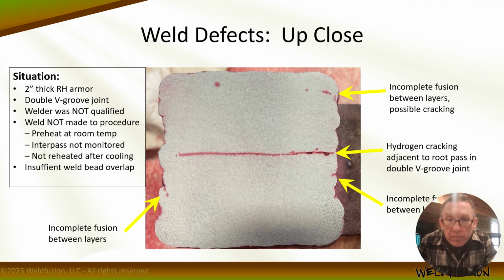Preheat was done at room temperature. Interpass temperature was not monitored between passes or after breaks. The assembly was not reheated after cooling, and poor technique resulted in insufficient bead overlap and incomplete fusion between layers. So this is an indication of just going back to basics and following the process and procedure, making sure that our welders are qualified and know how to make an acceptable weld joint, and we can resolve these issues.